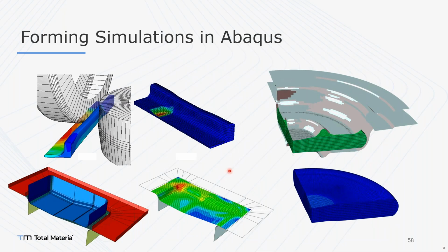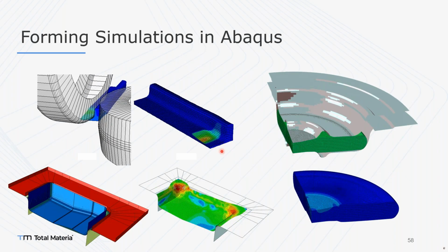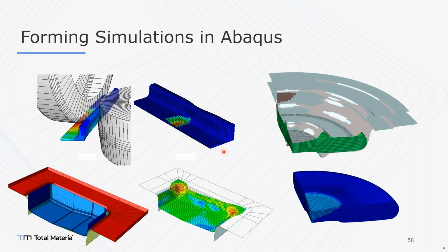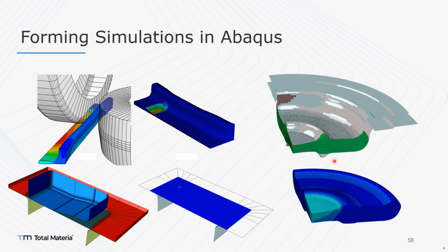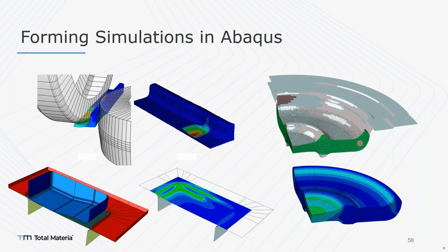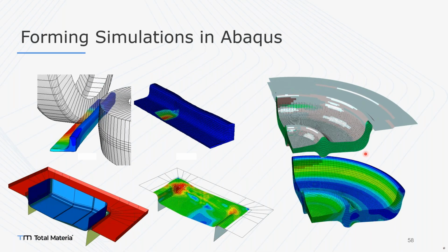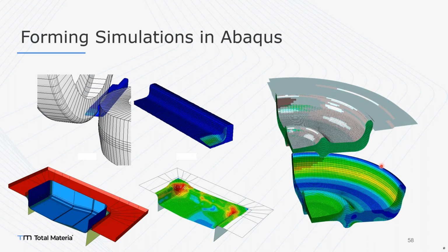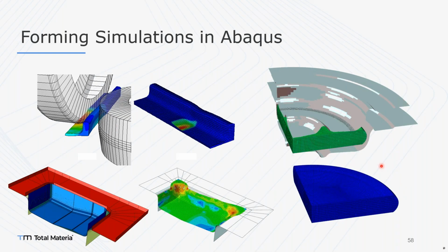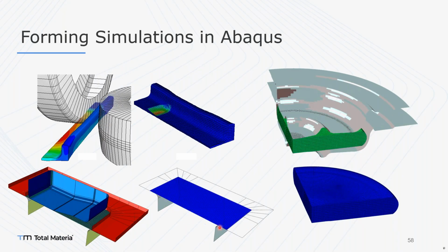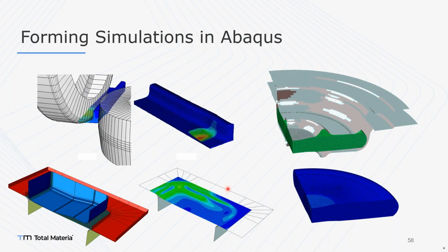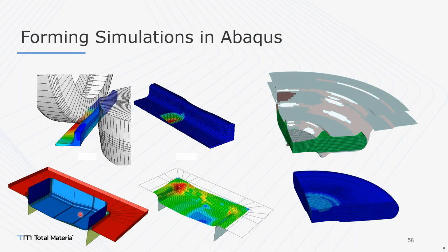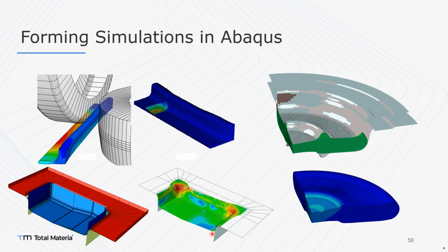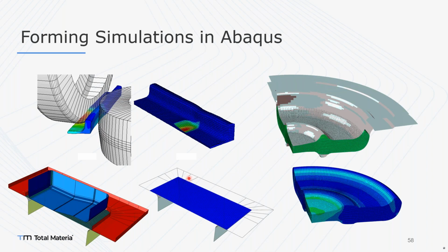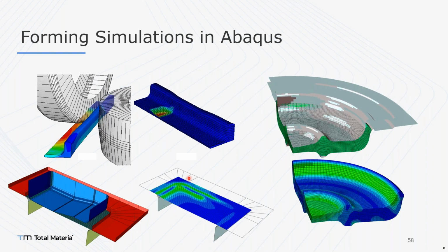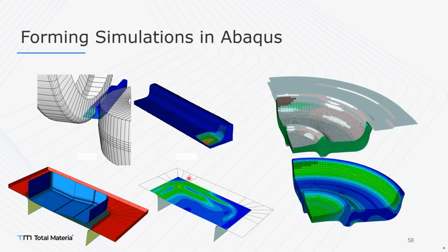As you can see, we have an analytical rigid here, and the forming part. The Arbitrary Lagrangian Eulerian method will be implemented here, and here is a Lagrangian model, but it could also be modeled as coupled Eulerian Lagrangian because of the high strain values, and the friction level is really dependent on the pressure in this analysis. Here we also have another analytical rigid die, but you can also model it as a discrete rigid, for example this one. You need to consider your mesh, and you can use remeshing tools or the adaptive meshing method to observe a more accurate solution.